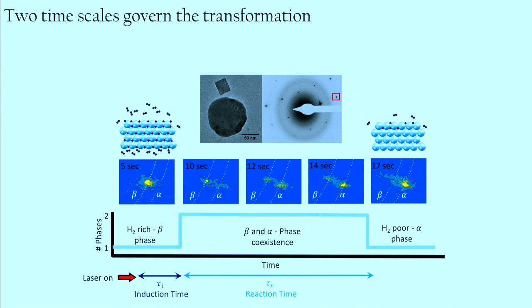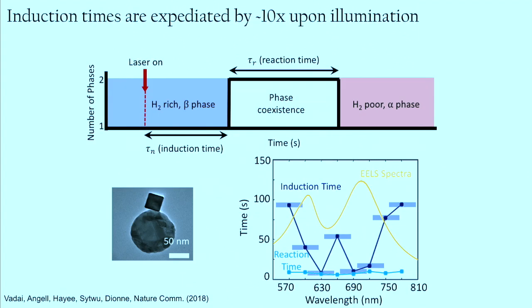There was a period that you saw in that diffraction movie where really nothing was happening. So we call that the induction time. And then we wound up having phase coexistence between the alpha and beta phases. And when we started that phase coexistence all the way through to the end of the transformation, we call that the reaction time.